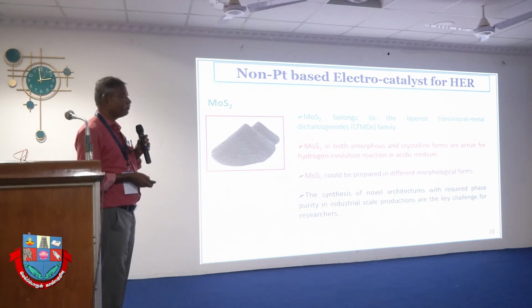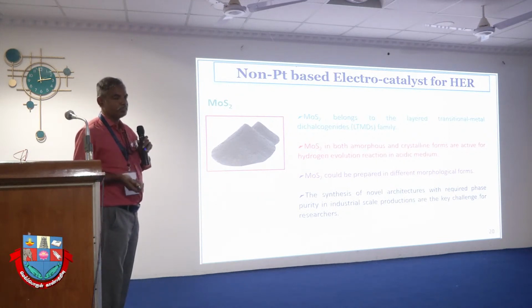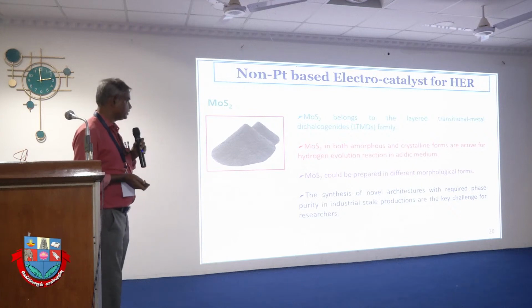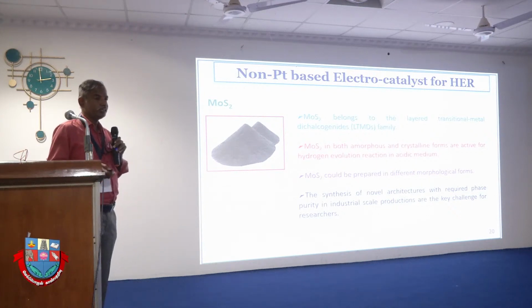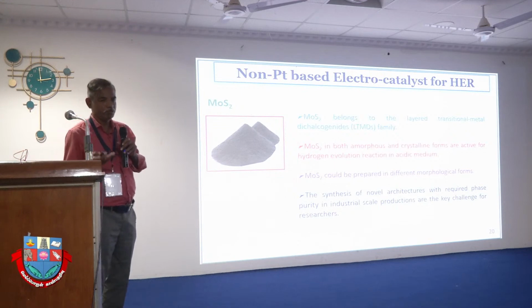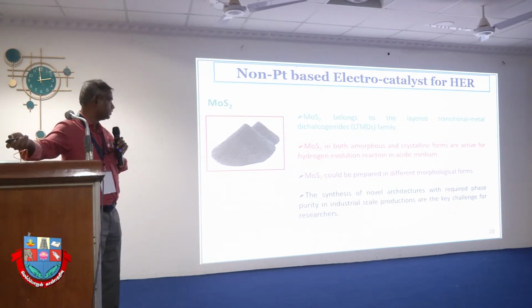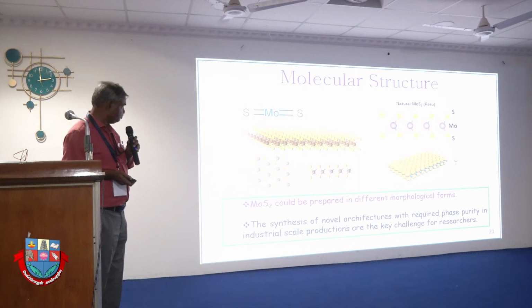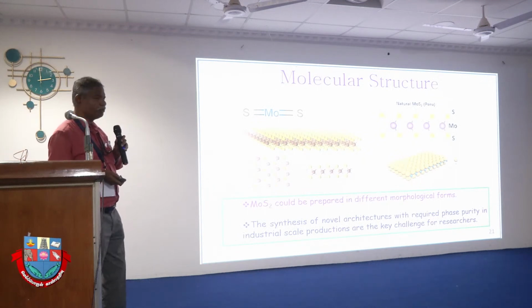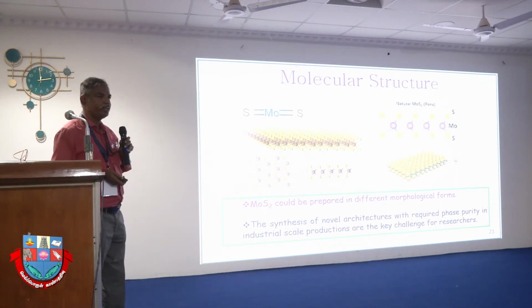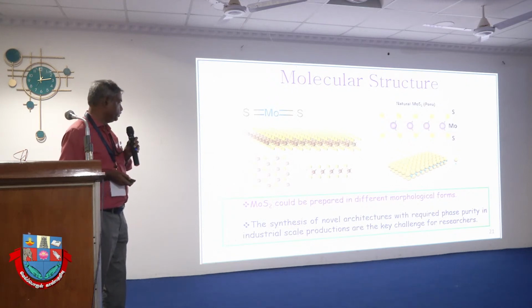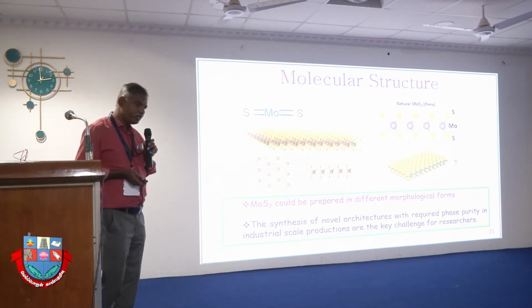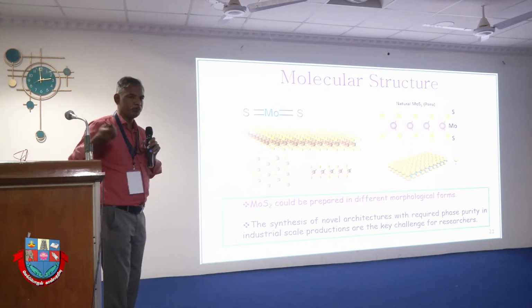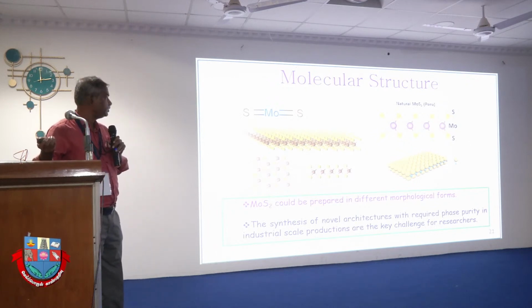And MoS2 could be prepared in different morphologies, because if the morphology differs, the surface area will be different. And for synthesis of novel architectures, a very important thing, at any scale, in any industry or laboratory, is that a material should be prepared in highly purified form without any impurities, so that we can use it for industrial scale applications. This is the structure of MoS2, where the Mo is sandwiched between two sulfur atoms. It's a layered material. We can take it layer by layer, but we can also prepare it in powder form and in different morphologies.